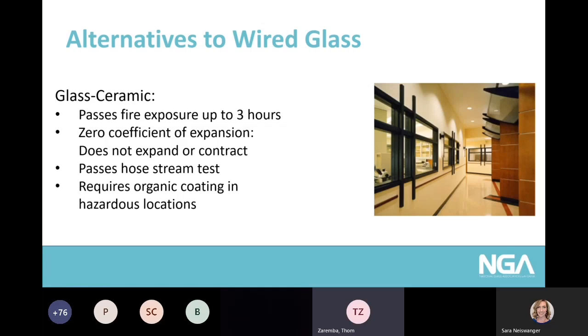So what are alternatives to wire glass in fire-rated applications? Well, one of the primary alternatives is glass ceramics. Glass ceramics has a zero coefficient of expansion. That means that when exposed to heat and then rapid cooling, it doesn't expand or contract, and therefore it won't break. As a result, because of its chemical composition and its molecular composition, it can pass a fire exposure in the fire test for as long as up to 3 hours. Now, wire glass, as I mentioned, is limited to 45 minutes, but ceramics can pass for up to 3 hours.